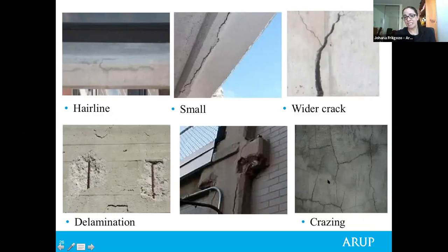And crazing, this is very thin cracks in a mapping sort of pattern. And they're mostly due to defects during the construction in the plastic state of the concrete.